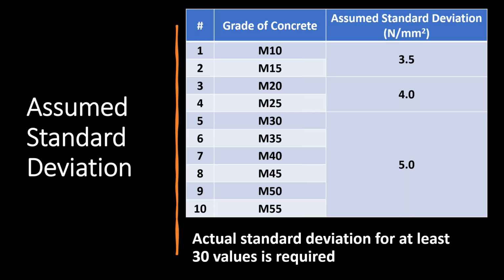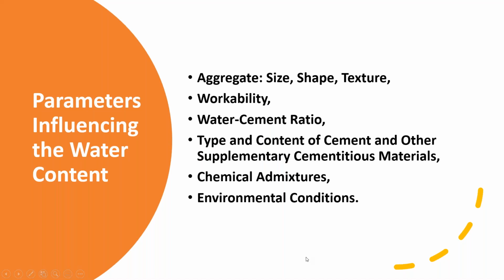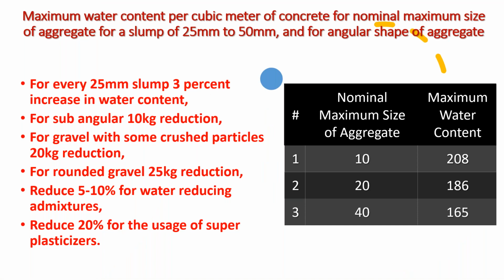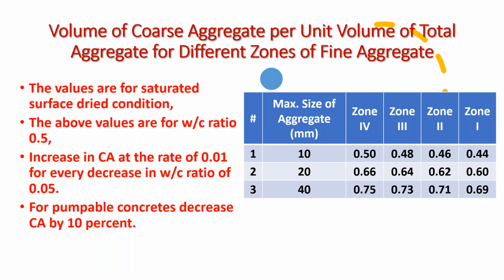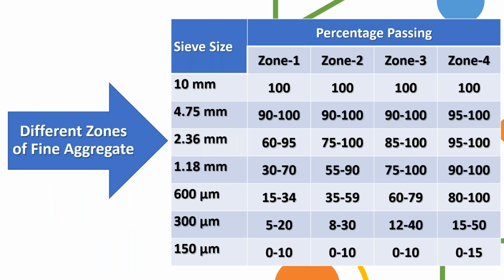These are all the values suggested for standard deviation. This is the assumed standard deviation, but actually if you have a minimum of 30 values, you can calculate your own standard deviation and adopt it in your concrete mix design. Okay, the parameters employed: these are again the same table that I explained earlier, and this is the sieve analysis result as per IS 383, zone 1, zone 2, zone 3, zone 4. I need not explain this.